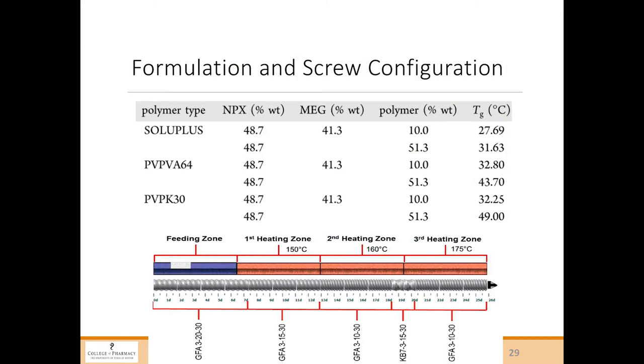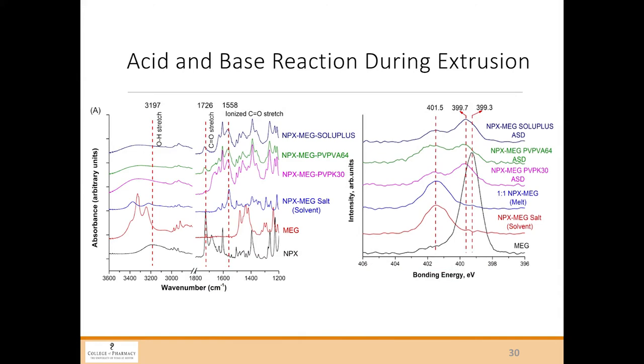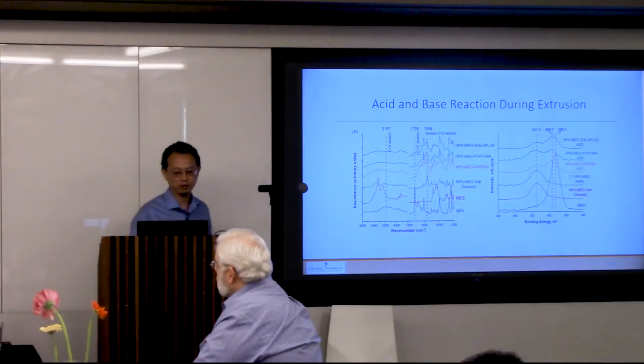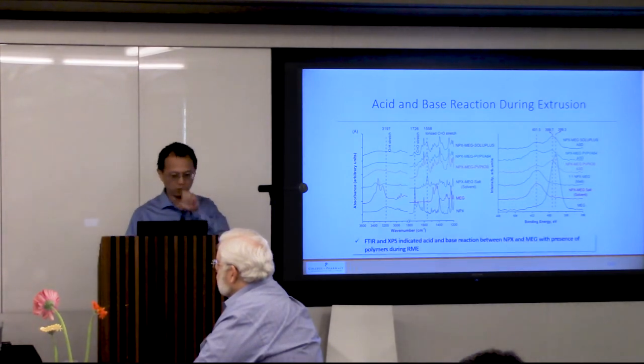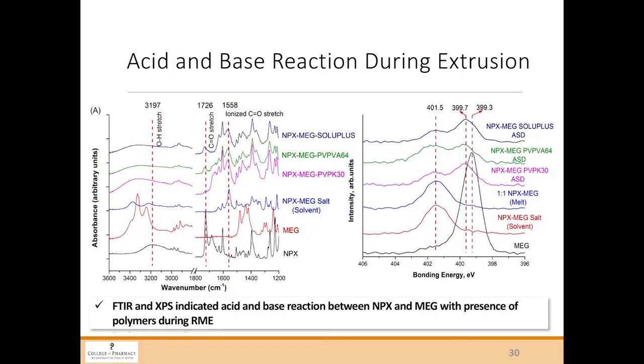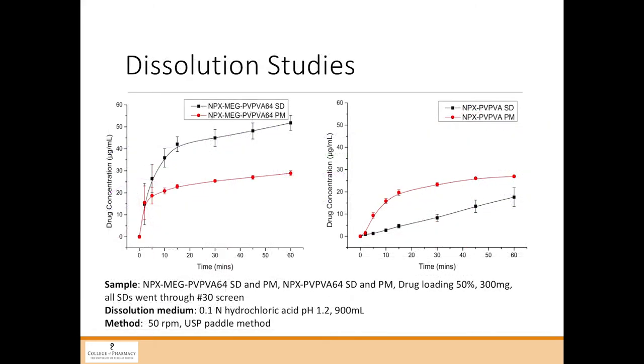So we're heating about 150 to 160 degrees C in the barrel. We don't use the die, we just catch the material, the solid one. In this extrusion, now we have polymers, and we see the same thing as far as naproxen, its carbonyl, the same type of ionizations, same type of reactions. And the presence of polymer actually did not interfere with the interaction between naproxen and MEG. We also use XPS to confirm the ionization state of naproxen. That gets confirmed.